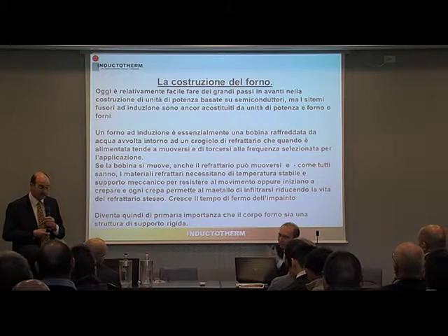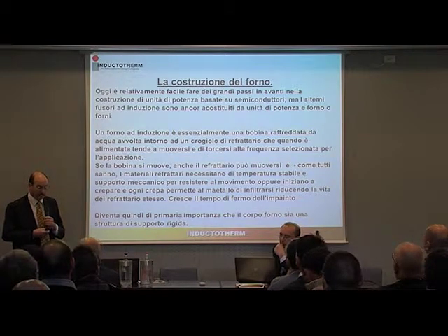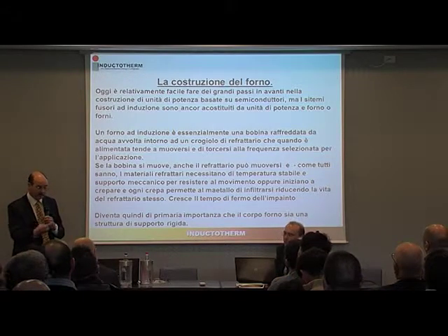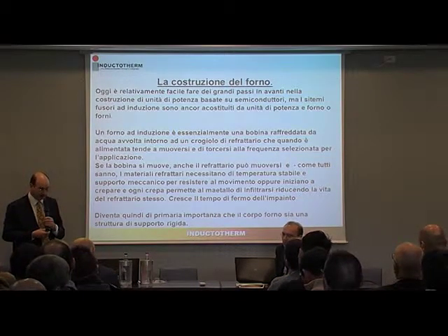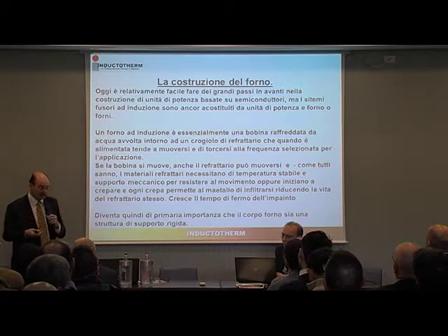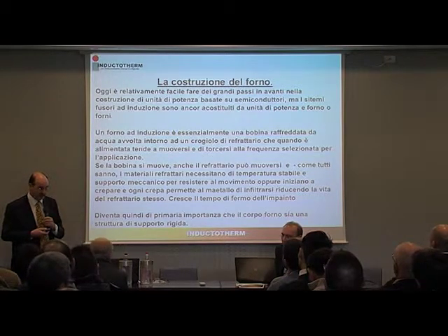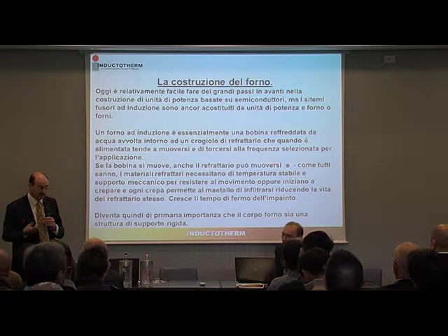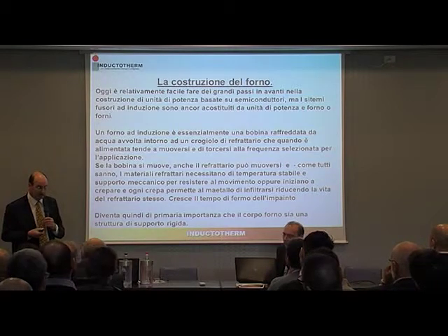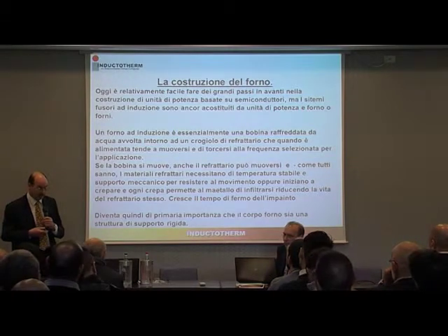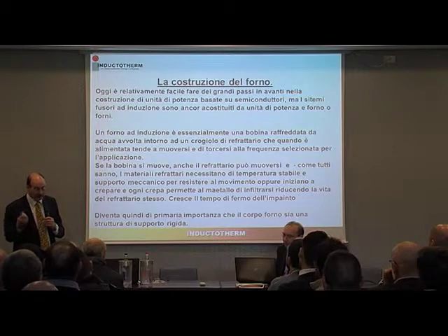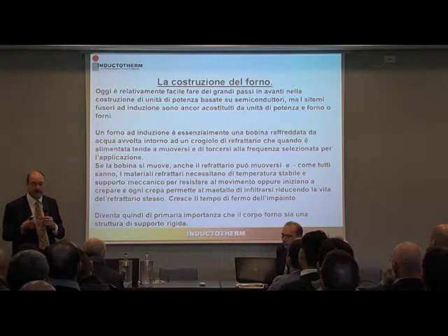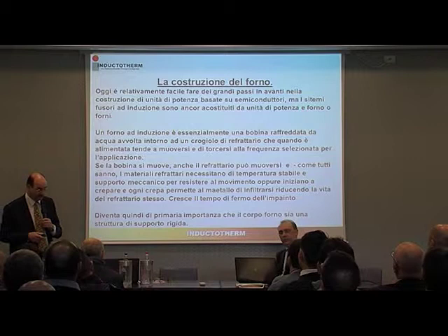An induction furnace is fundamentally a copper coil wound around a refractory crucible. And when supplied with all this power, it will attempt to jump up and down at the frequency of the power supply. If the coil moves, the refractory is allowed to move. And as we all know, refractories like stable temperature and support to resist movement. Or they crack. Cracks allow metal ingress. Metal ingress reduces the refractory life, and downtime is increased.